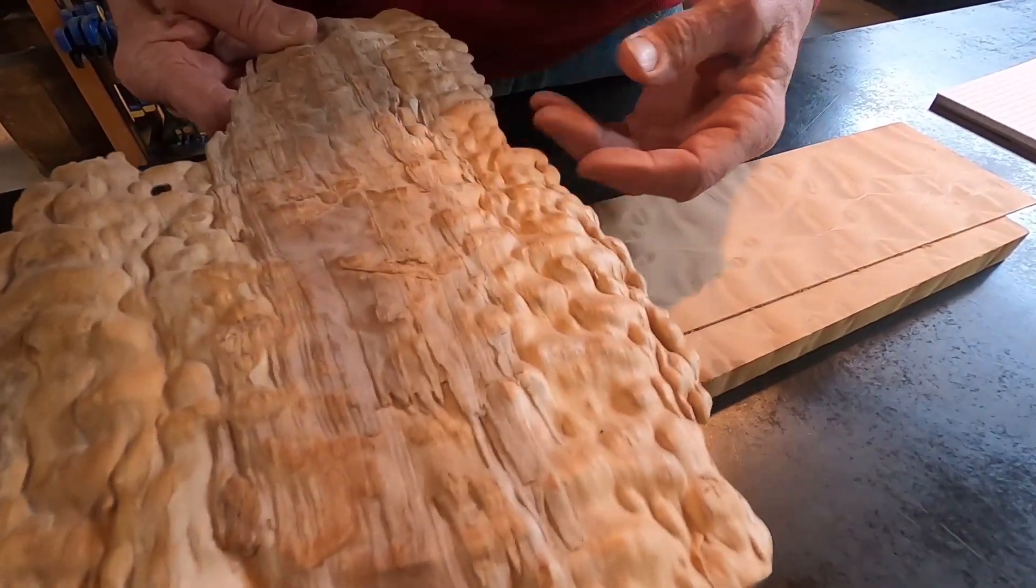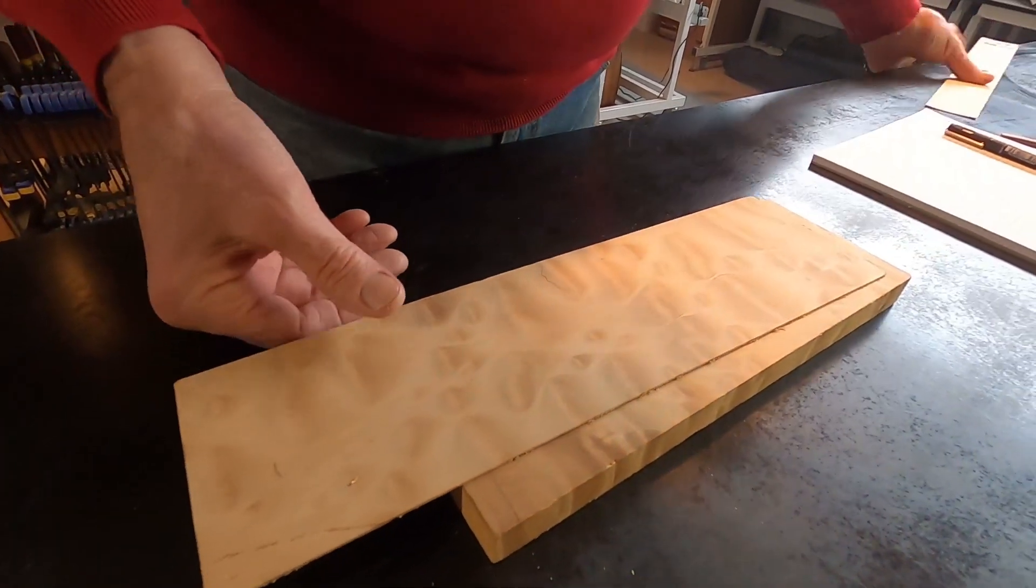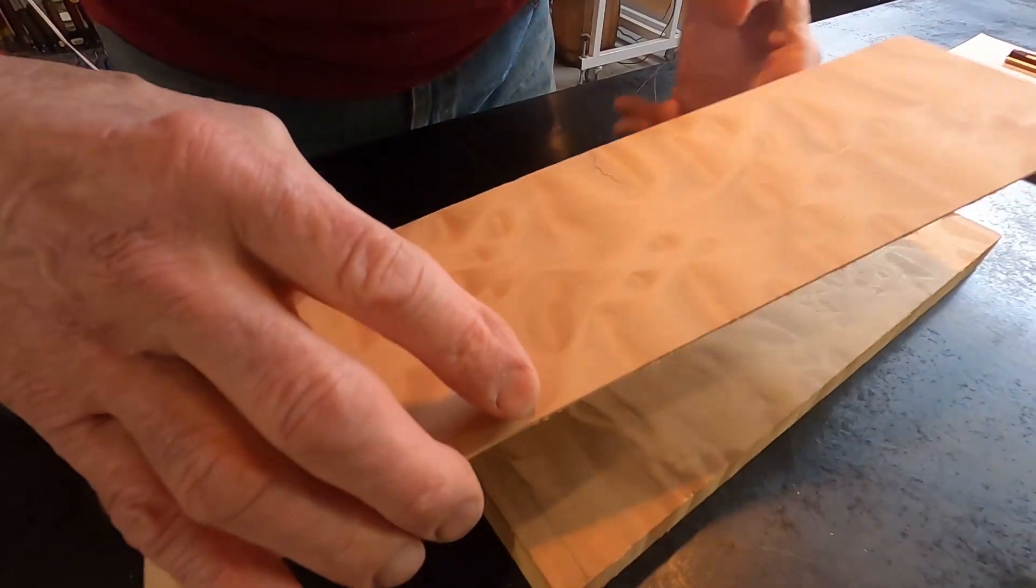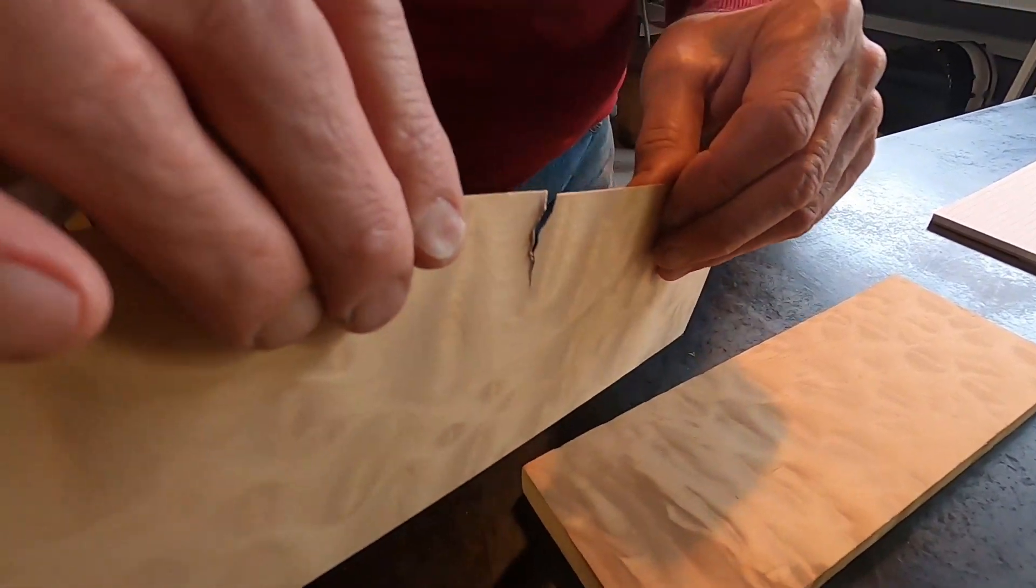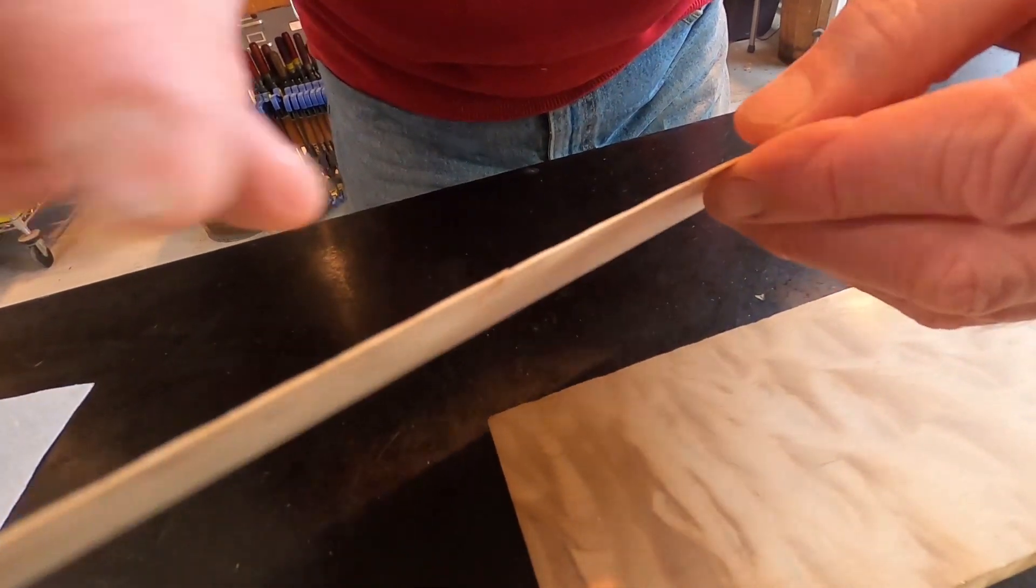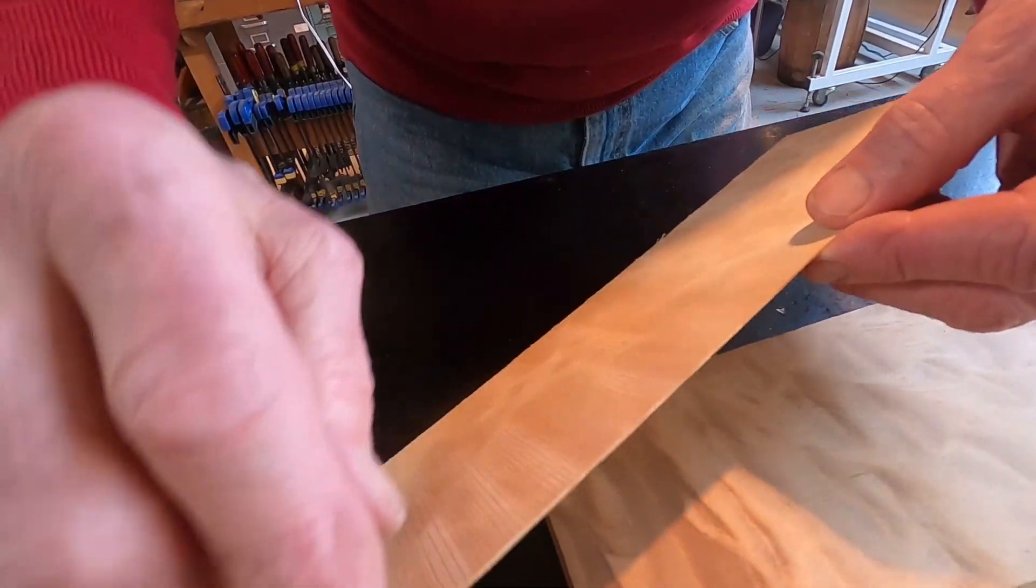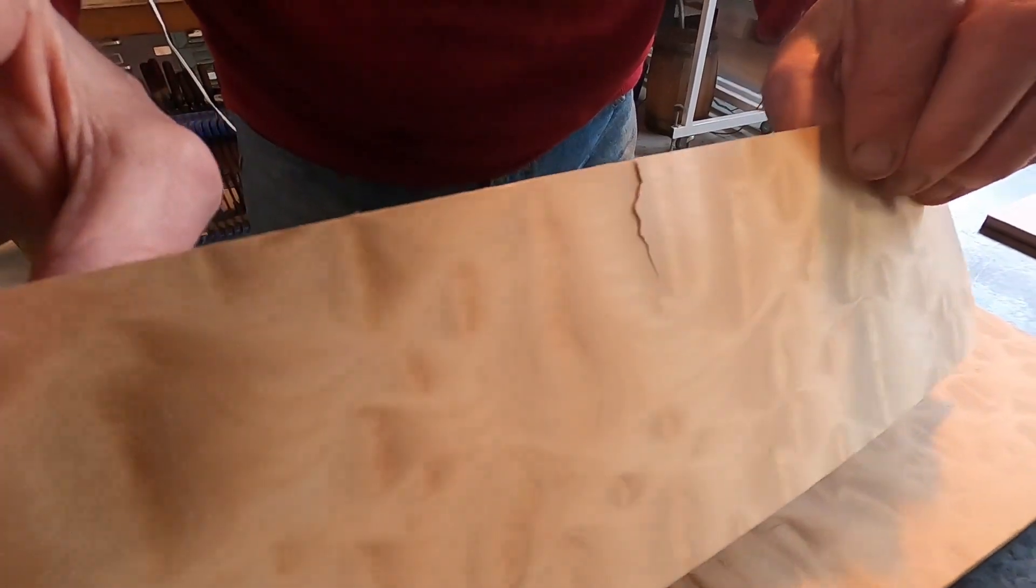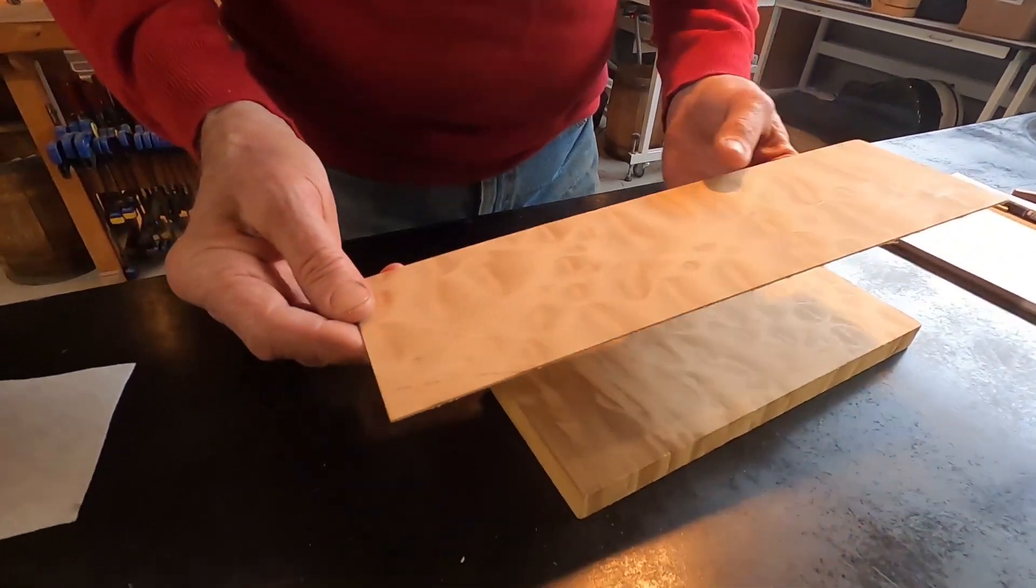So what that means is that instead of nice straight grain lines like we have in this example, a piece of poplar, we have grain lines that are going all kinds of crazy ways. And you can see here the failure of this thin piece across the grain. Woodworkers call this short grain. In other words, the grain lines, instead of being along the length of the part, are going at an angle. And this is a pretty abrupt angle here. And if I were to give this almost any force, it would just burst straight across the part in a jagged break. So this presents an extra challenge when we're bending figured material for guitars.